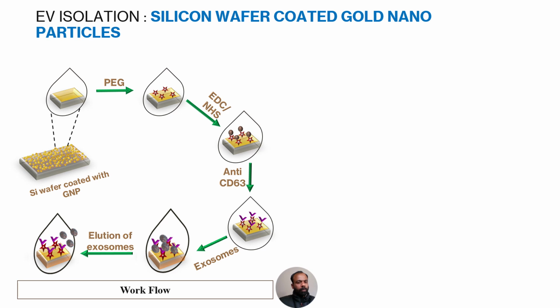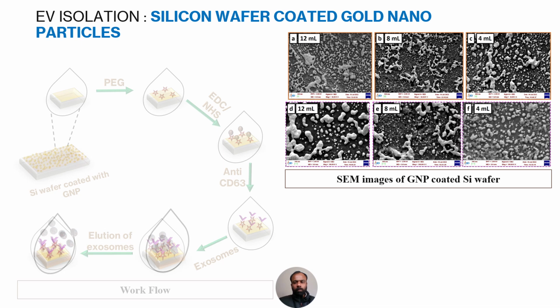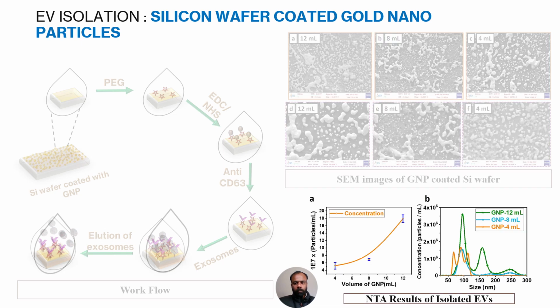Silicon wafer coated with gold nanoparticle can also be used for isolation of extracellular vesicles. The SEM image shows the silicon wafer coated with different volumes of gold nanoparticles. It was concluded from the NTA experiments that with the increase in the volume of gold nanoparticles used for coating the silicon wafer, we can significantly increase the number of extracellular vesicles that are isolated.